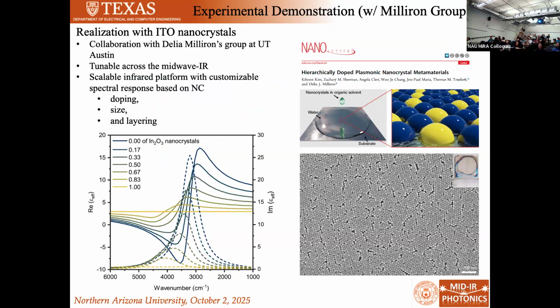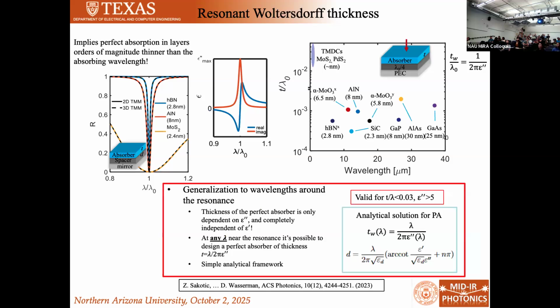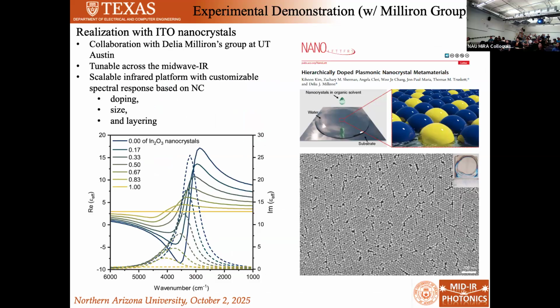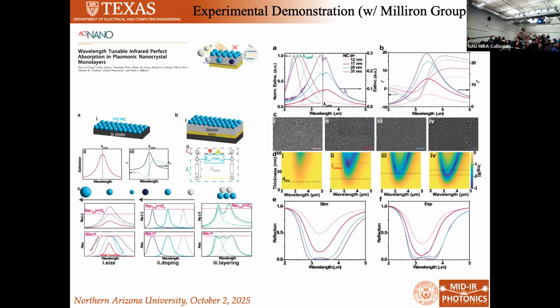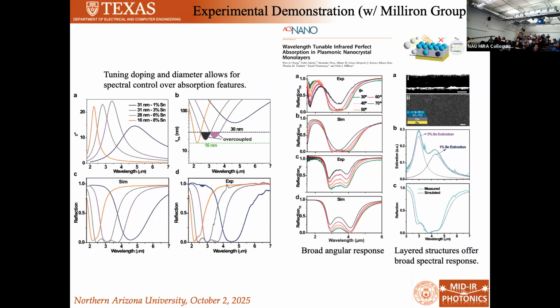It looks very similar to what we need to get this perfect absorption in thin layers. So we thought, well, okay, if we put these layers of nanocrystals on our open cavity structure, we should be able to actually get perfect absorption. And that's in fact what we see here in a single monolayer of this material. And this is pretty angle insensitive.